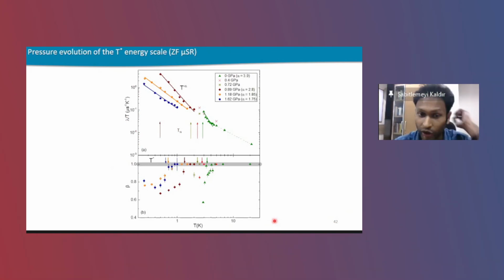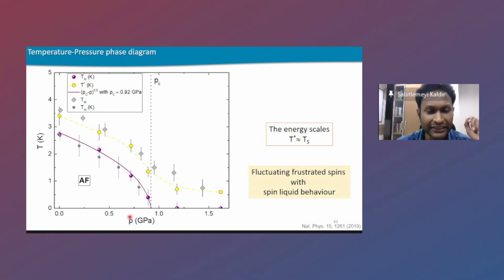And as I told you, this T star temperature, below which the beta starts deviating from 1, also changes as a function of pressure. As I told you, the T star temperature is exactly mimicking this TS, below which you would expect some spin liquid behavior. So this is the full phase diagram. You can see I have plotted this T star from our experiment as a function of pressure. And I have also given the values of these gray squares from another paper, which is the pressure dependence of this TS, where you have the hump. You see that they are quite matching with each other. So indeed, this T star and TS lead to the same energy scales.